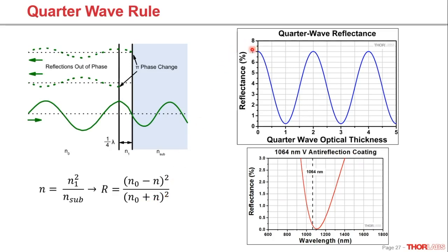So we see here, in the case of a 1.72 index material, if we were to apply magnesium fluoride, which is typically a 1.38 index, we would see the percentage drop from 7% and diminish to almost 0 as we arrive at that quarter wave optical thickness. And as we continue to deposit the material, we would see it increase back to the initial reflectance of the bare substrate again, and continue to oscillate, so on and so forth from there.